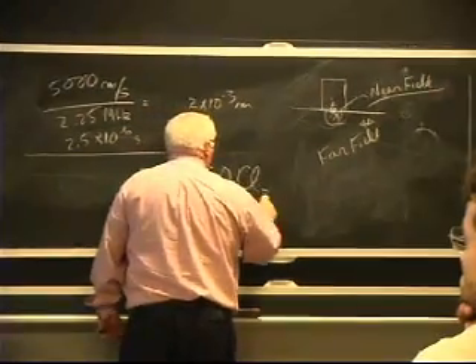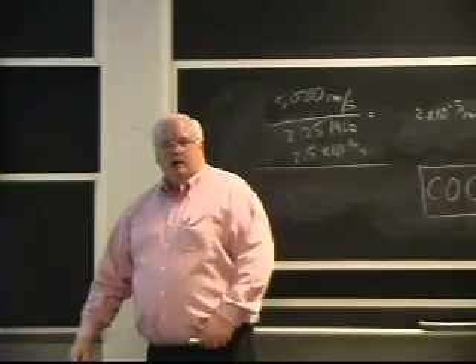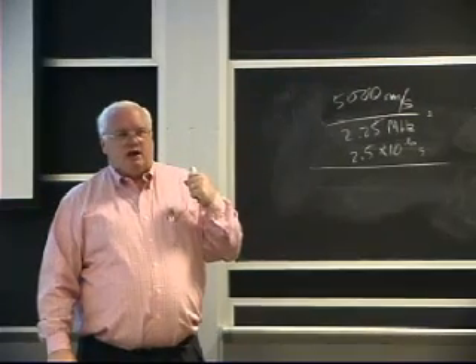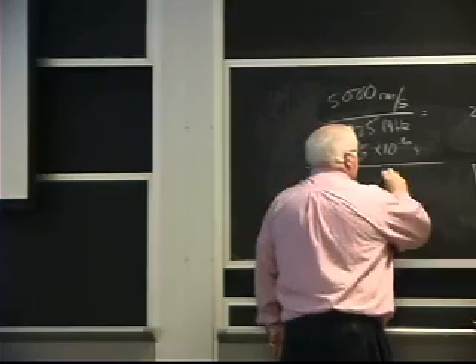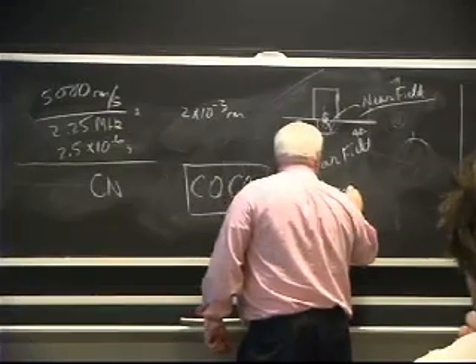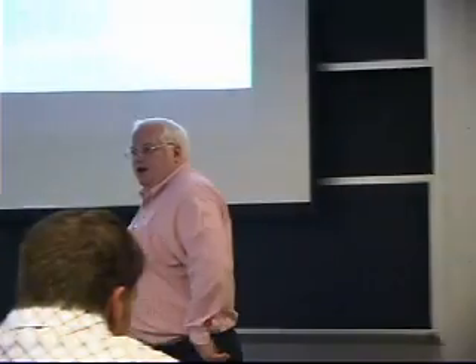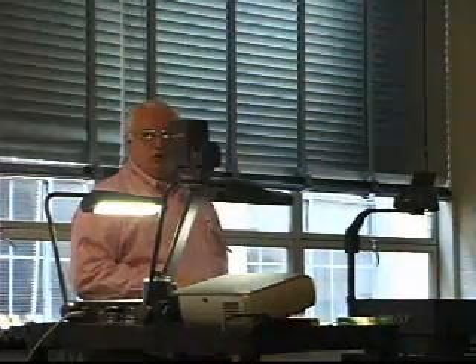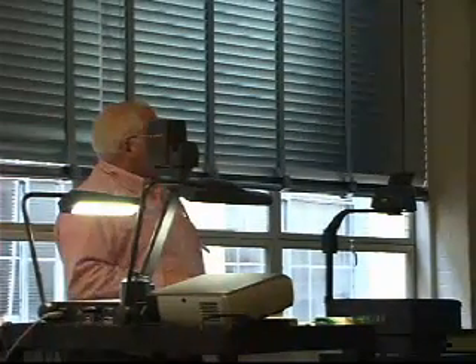If you use a chlorinated solvent and you look for cracks and then you weld over the area afterwards, which you often might do, then if you're welding steel, chlorine plus carbon plus oxygen in the steel gives you this compound, carbonyl chloride, which has another name. Anybody know what the name of this is? It's a gas. No, it's not cyanide. Cyanide is CN. This is actually maybe even worse. It's phosgene. And phosgene was one of the gases they used in World War I to gas the soldiers, right? So you don't like to clean steel before welding with chlorinated solvents, because when you weld later, you're going to expose the welder to phosgene. In any case, they typically use non-chlorinated solvents. In fact, in the nuclear industry, they require that the non-destructive test solvents be sulfur and chlorine free.